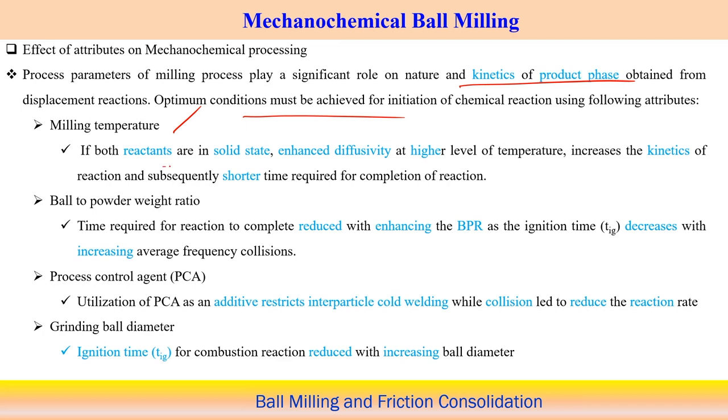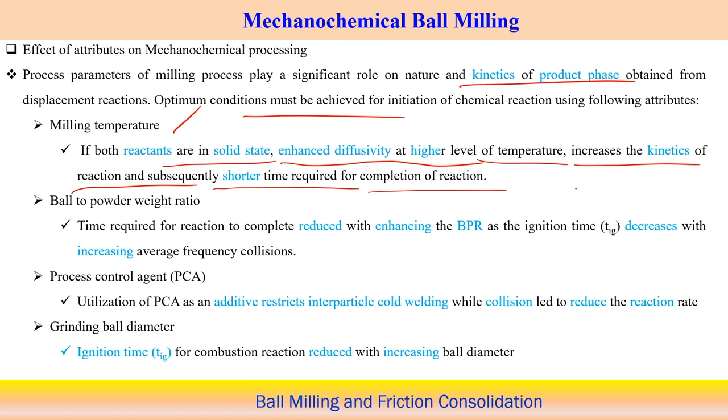If both reactants are in the solid state, enhanced diffusivity at a higher temperature usually occurs. So diffusion might be much more if there is an increase of the milling temperature, which promotes a high amount of diffusion. At the same time it increases the kinetics of the reaction, and a shorter time is required for the completion of the reaction. So when you accelerate the diffusion process, you are increasing the kinetics of the reaction, and when the kinetic rate increases, the time required will be less. That is the effect of the temperature.